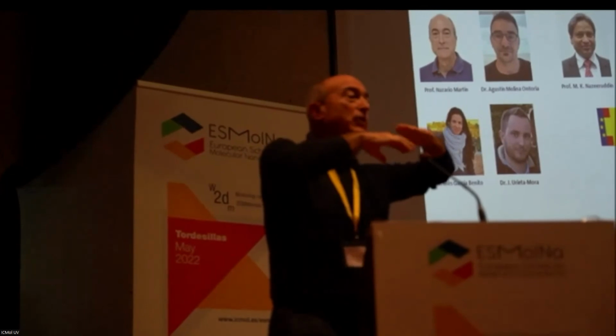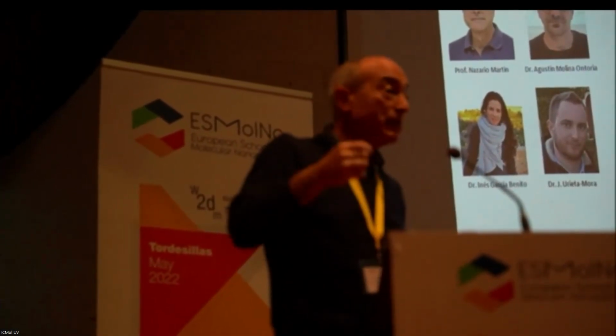Then you see, you are calculating. Well, you have shown some HOMO-LUMO values, but these are calculated assuming that you have no solvents, not anything. But if you are doing that from solution, the calculations should change, and then, for example, the interaction you have put between the molecules will not be. This is a very good point, because always when you have the HTM alone, that is a calculation in the gas phase, or by also simulating the solvent. But what is interesting, and you are right in this regard, is when you have it in contact with the perovskite, probably the interaction between phases makes the difference, because probably the HOMO-LUMO levels can be modified a little bit according to this interaction.